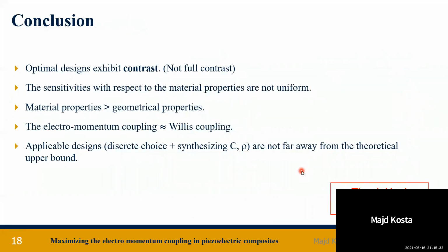To conclude, we can say that optimal design exhibits contrast, but not full contrast. The sensitivity with respect to the material properties is not uniform. Material properties are more significant than geometrical properties for the electromomentum coupling. And we also proved that the electromomentum coupling had the same contribution as the Willis coupling. And we have proved that applicable design gives values of W that are not far away from the theoretical upper bound.